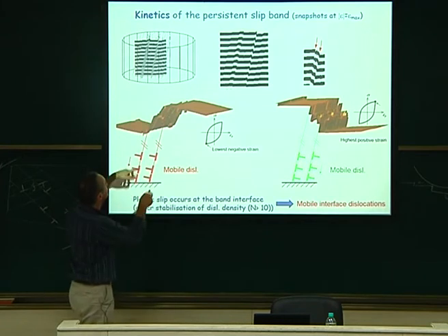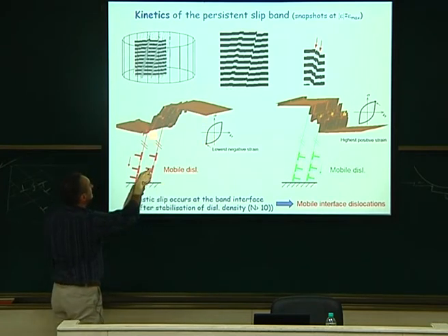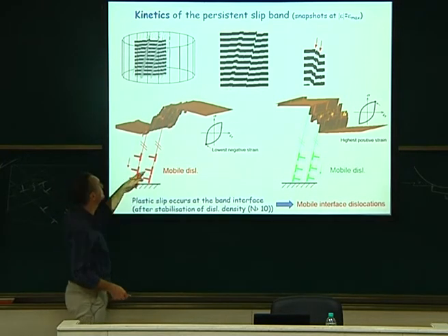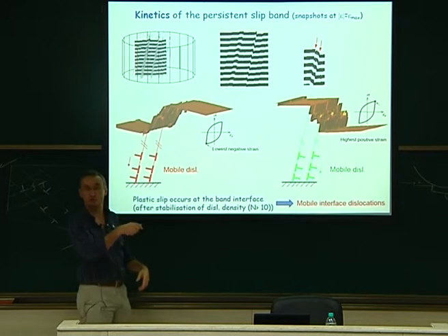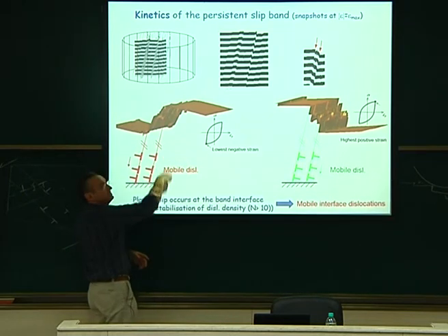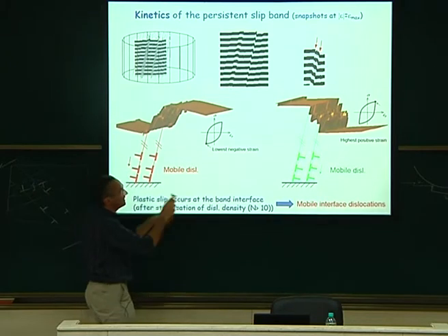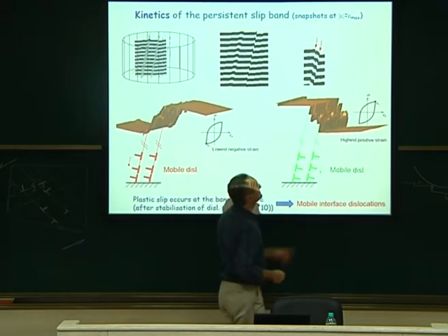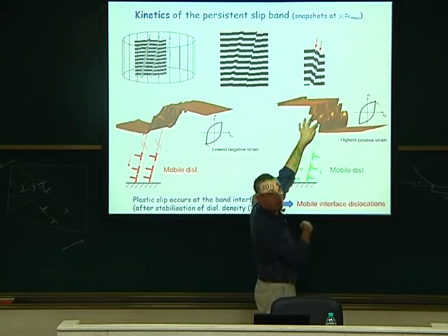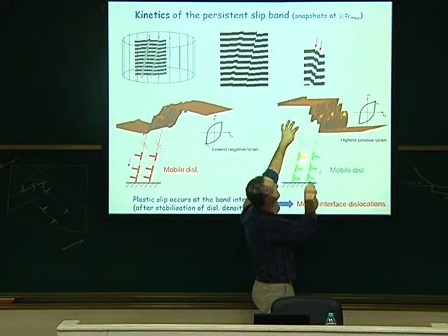If you look at the surface, when it is totally negative, you see a big step here and a big step there. It means that you have many mobile dislocations which have been active here. Typically a Frank-Read source was active here and emitting many dislocations that will all localize the plasticity here. And when you reverse the loading, when you are in opposite state, everything will go back. It will unpile up. You are piling up and unpiling up your dislocations here at the interface, and you will create the same step, opposite sign.